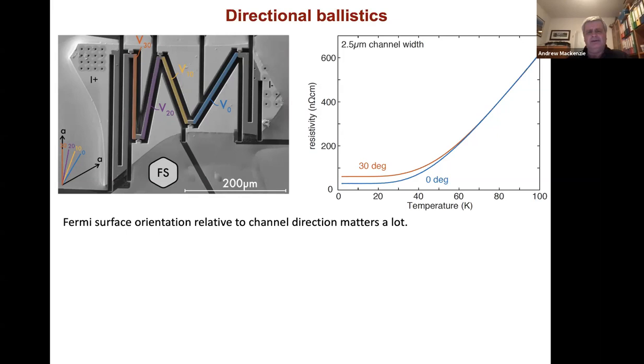It turns out that the Fermi velocity is more or less isotropic around that Fermi surface. So we slightly erroneously concluded that it wasn't going to be a big problem, but we still went on and checked it in some future experiments anyway. And in experiments done by Maya Bachmann during her thesis, she was able to show that it's far from a negligible effect. In fact, it can be a huge effect.